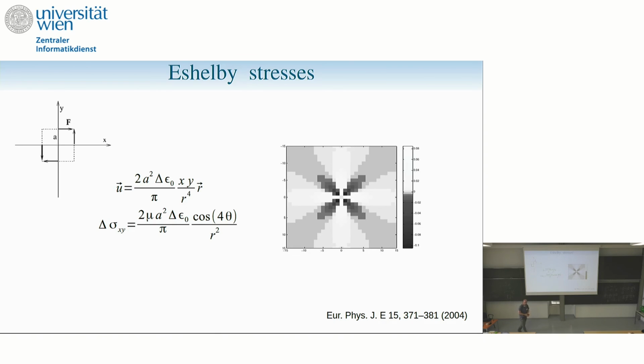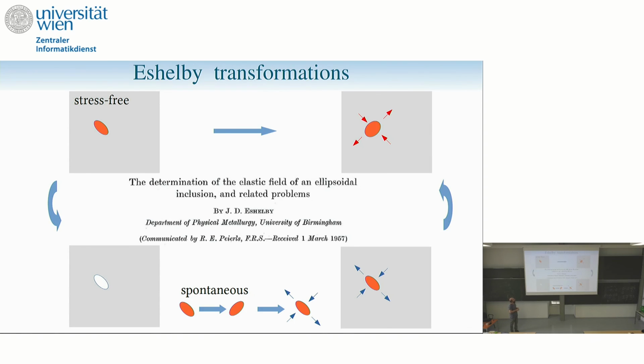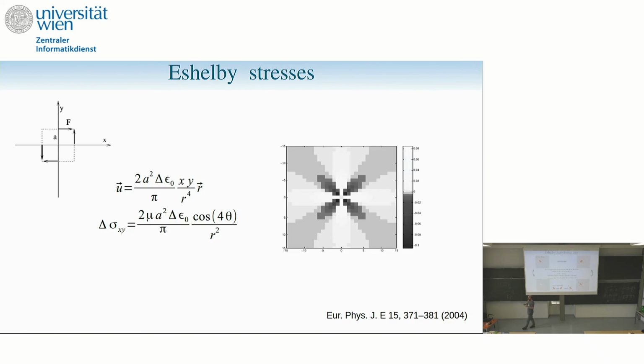People often speak about quadrupole. It's not a quadrupole. Right? It has a quadrupole shape, but it's the response to a set of forces, and this set of forces is a dipole. So that's something very strange: if you construct an analogy with electromagnetism, this set of forces corresponds to an elastic dipole, and the elastic response of an elastic dipole turns out to have this cos 4 theta symmetry, right? So you often hear people speaking of the Eshelby quadrupoles. I will speak about Eshelby dipoles, which have, yes?